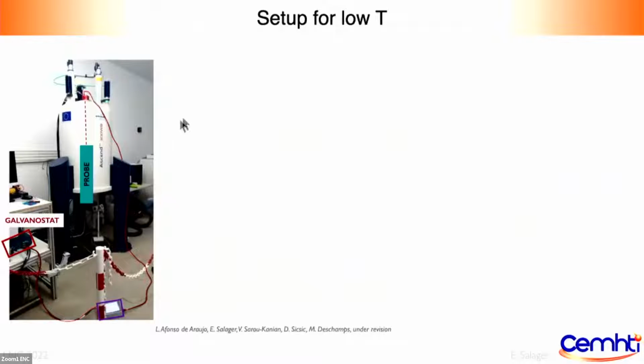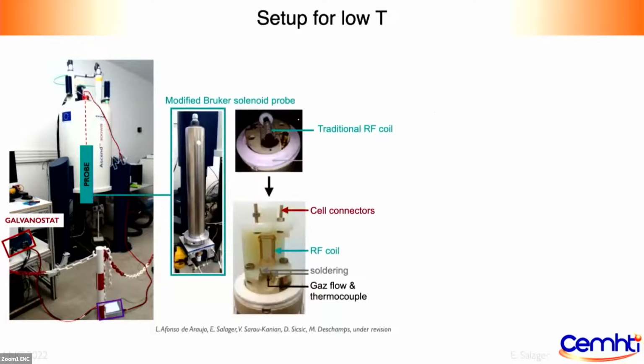And then we had to change our setup for low temperature. So this time we cannot remove the dewar because we need to control temperature. And so what we did is that we went for a Bruker solenoid probe, which is heavily robust to low temperature. And we removed the traditional RF coil, and we inserted instead a saddle coil that would allow us to have our battery, our electrochemical cell inside. And so the cold gas is coming from the bottom with a thermocouple here and everything to control temperature.